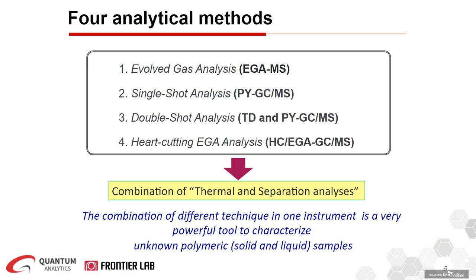You could also perform single shot, which is flash pyrolysis, an instantaneous pyrolysis of a sample. On one pyrogram, you observe polymeric pyrolysate, any volatile compounds, and their decomposition products. The third mode of operation is a double shot analysis that operates both the thermal desorption and the instantaneous pyrolysis. You obtain the separation analysis chromatogram of volatile compounds and the pyrogram of instantaneous pyrolysis in one set. The last mode of operation you could perform is the heart-cutting EGA GC-MS, which is based on the information from your EGA data, in which you selectively operate the thermal desorption or temperature program pyrolysis in each temperature fraction where the gas evolves and individually obtain separate analysis.